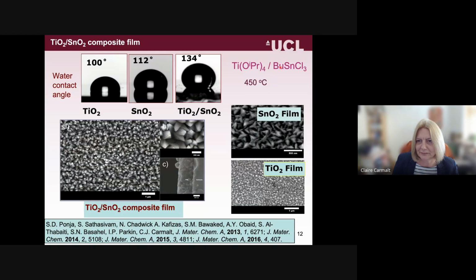Or if we take this as a mixture in our AACVD bubbler, you can then add in ethyl acetate, do the AACVD at 450 degrees, you form a TiO2-SnO2 composite film, and you can see you get this very, very unusual morphology. We originally looked at this for photocatalytic applications, and it really did enhance the photocatalysis, we think, because of such an increased surface area. But also looking at this, we thought it could work very well for an application known as SLIPS, which is slippery liquid infused porous surfaces.